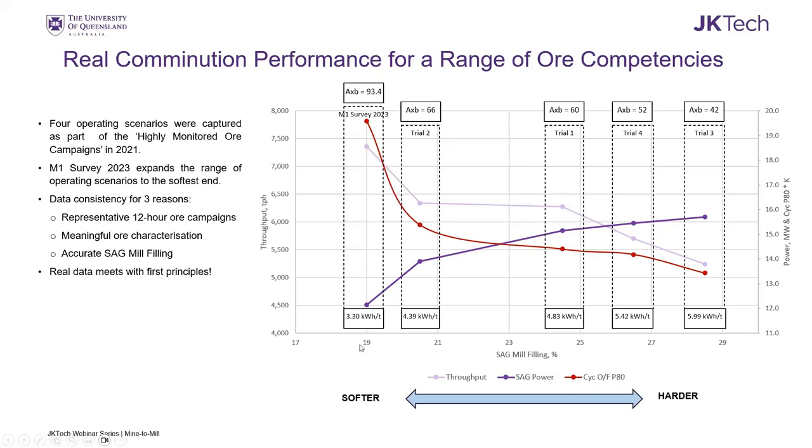Whereas with the very soft rocks, you get very low mill filling, very high throughput, as you can see, but also very coarse grind size. Because again, two things: high throughputs and coarser transfer sizes to ball milling caused by the low mill fillings in the SAG mill, which represents shorter residence times in the SAG mill. Less abrasion breakage is promoted.